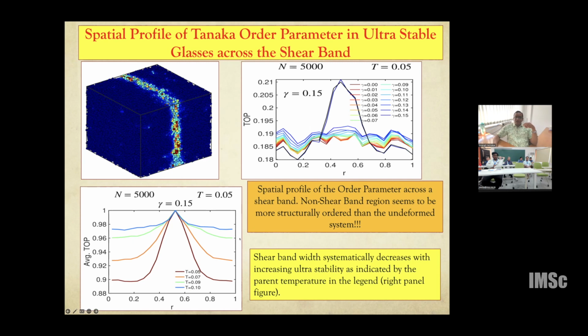If you prepare your glass from a high temperature liquid, then you get a shear band which is much more diffuse. But if you get it in a well quenched glass, that will have a shear band which is significantly narrow. So with this kind of framework, we are planning to study how the shear band width increases as you deform further after the shear band forms. And what are the other parameters which control this shear band width? And what is the scale that appears here? Is there a natural scale that controls the thickness of the shear band? Some of these questions are not clear to us, and hopefully we'll have an answer in the near future.